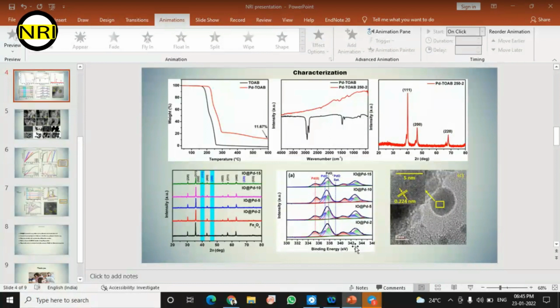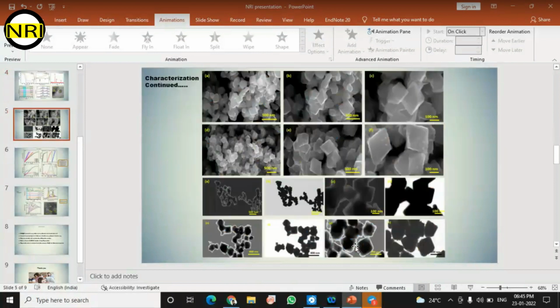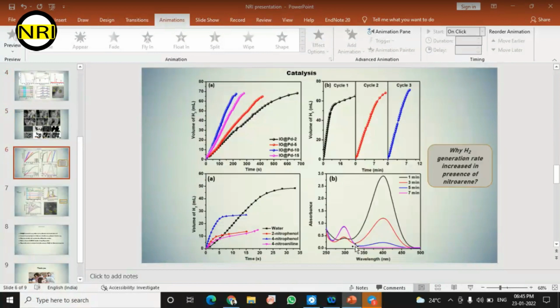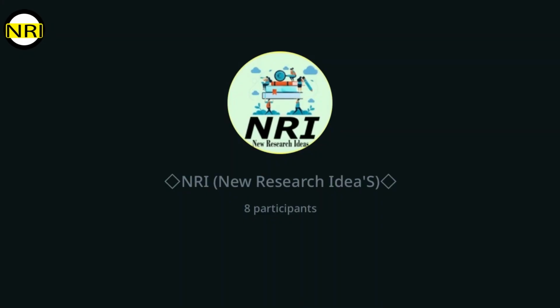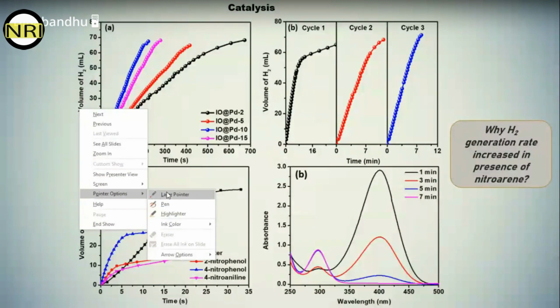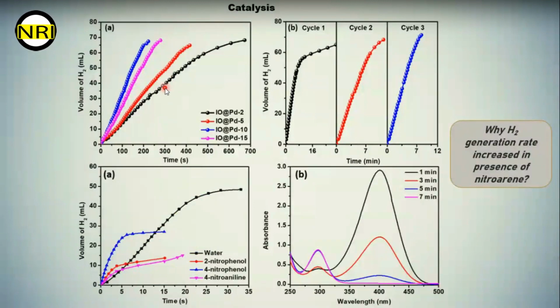And this thin layer doesn't aggregate. It aggregates when I deposit palladium beyond 10%. You can see here, black is for 2% palladium, red is 5, blue is 10, and 15 is this magenta color. We can see the trend that with increasing palladium the rate is increasing, right? But why is the 15% rate decreasing? This is due to